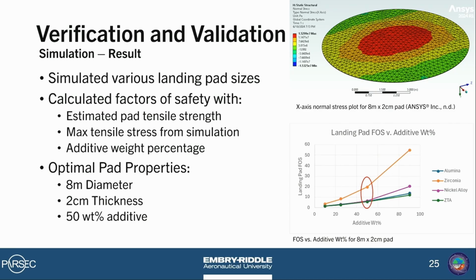Now, it is important to note the assumptions for this model are heavily idealized. The landing pad will more than likely have flaws, pores, and voids present if it is formed through this process that will create high stress concentrations. Nevertheless, the high factors of safety that we are seeing do show at least some promise for this solution.